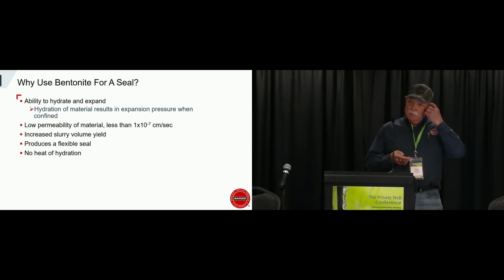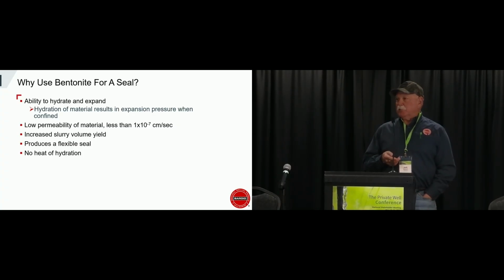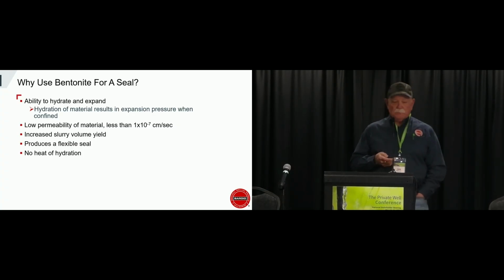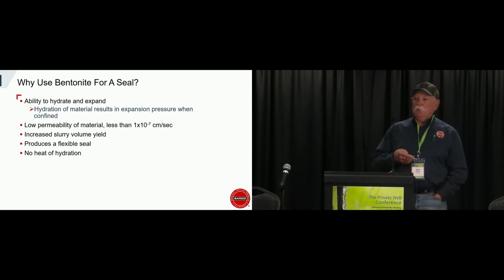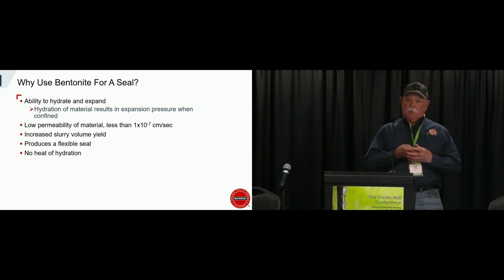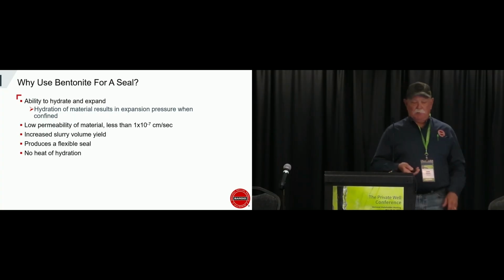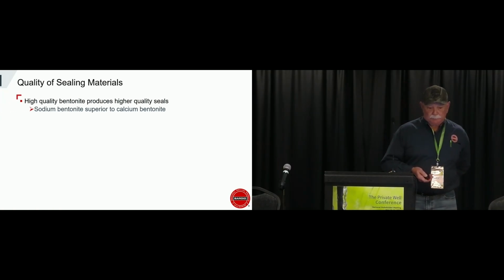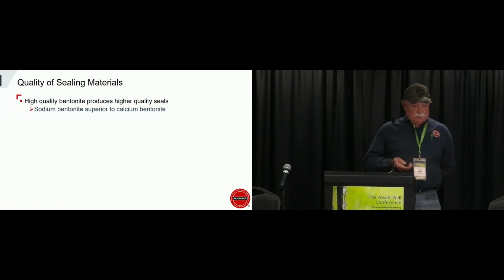And the heat can sometimes be excessive enough to deform plastic pipe, and also with steel pipe, because as the exothermic reaction goes, it gives off heat. So if you have steel pipe, it actually expands the steel a little bit, and as the cement cures, the steel contracts. So there you have a microannulus, so your seal isn't what you need it to be. So the high quality bentonite produces higher quality seals.